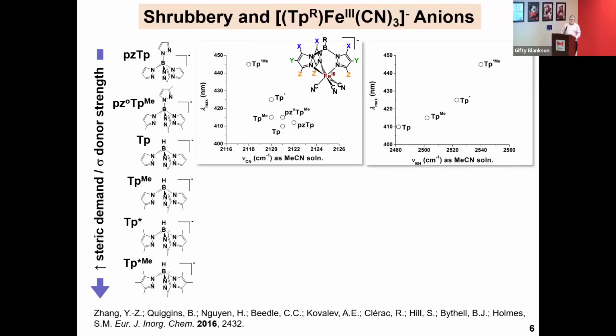It's the cyanide. So while many people would think that these ligands are just there for the ride and taking up space, they actually serve a critical role in the electronic and magnetic properties. In that if the cyanide goes to high energy, that means you're not putting much electron density into the CN triple bond. But in the opposite sense, it's going to the BH bond stretch. And so as one goes up, the other goes down. You get a push-pull type electron density. Right. So this allows us to do a lot of really cool chemistry.